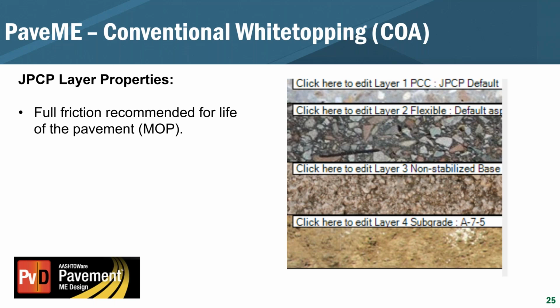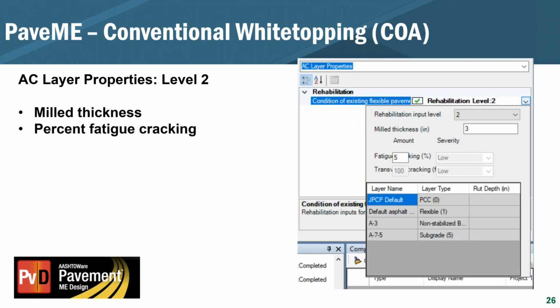The other thing is what's considered to give you a good prediction. The manual of practice recommends that you assume full friction between these two layers throughout the life of the pavement. So unless you have strong evidence otherwise, I would follow the manual of practice and assume full friction between these layers. Okay, so then we drop down from our overlay into that distressed asphalt layer.